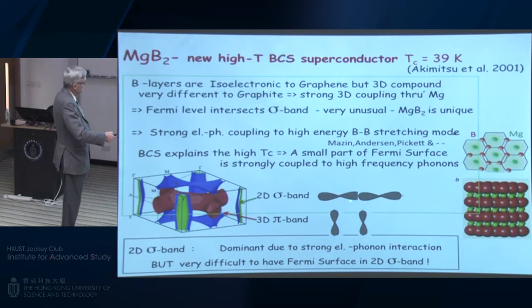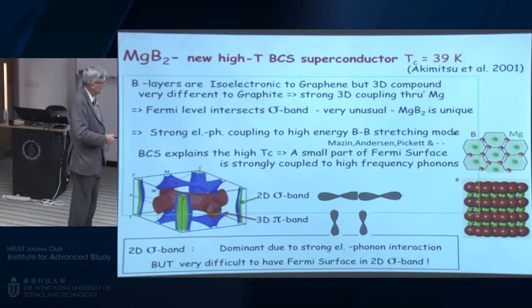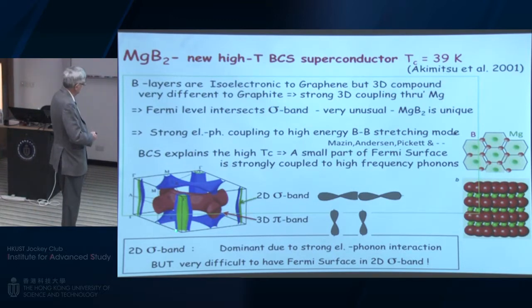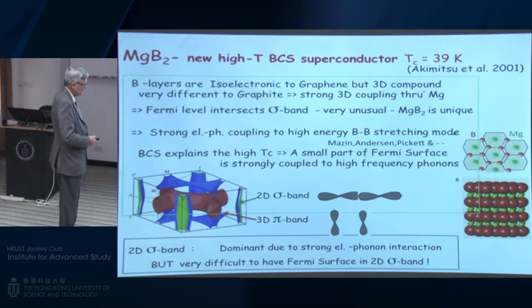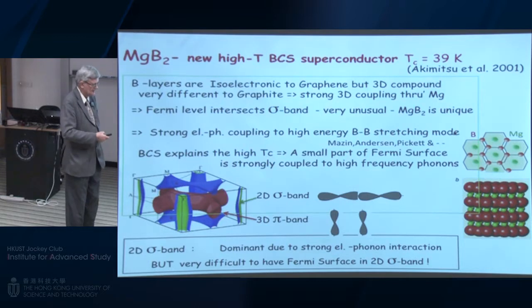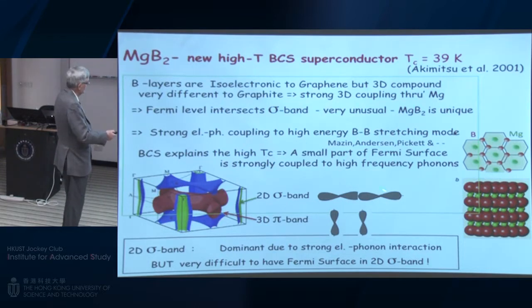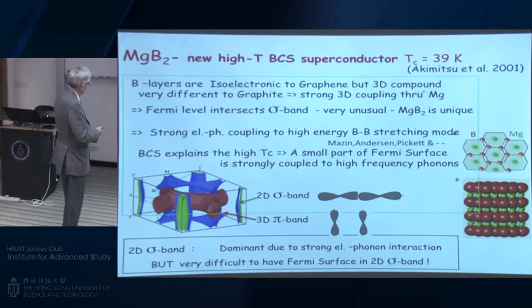And secondly, of course, because boron is such a light atom, these have very high frequency. So with BCS theory, you can explain this. It's a beautiful example for the BCS theory. But the question is, how did it avoid this trap that I mentioned earlier of a crystal instability? And this was obtained because you just couple to a small piece of the Fermi surface and to one very specific phonon, namely this breathing mode in the sigma band. By doing that, you can avoid an instability of the total crystal, but at the same time, you can couple these two strongly and generate a high transition temperature.